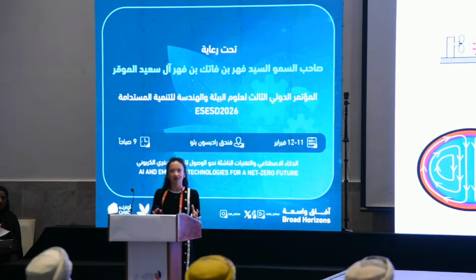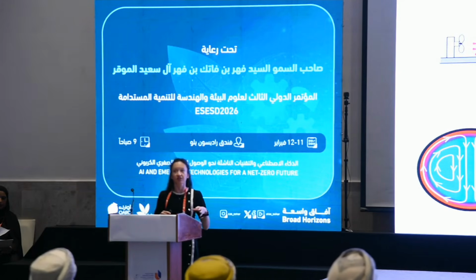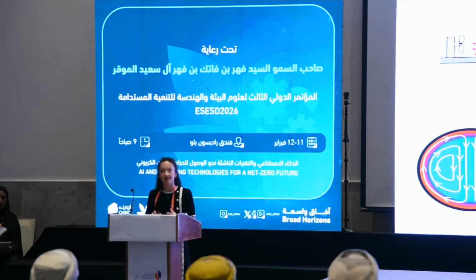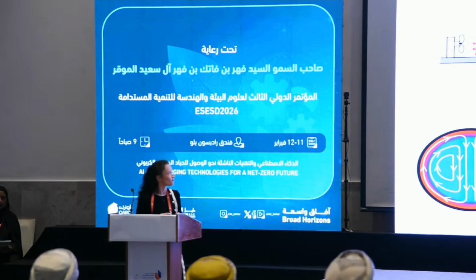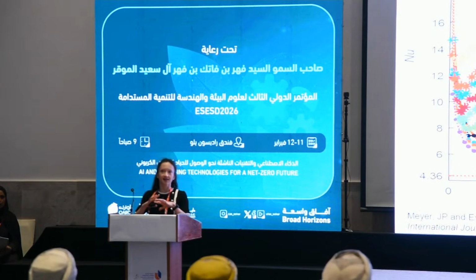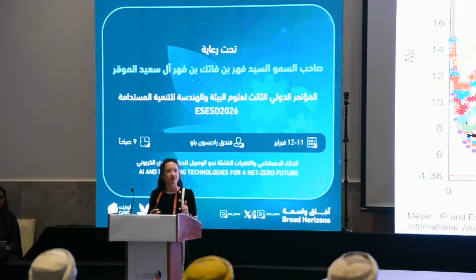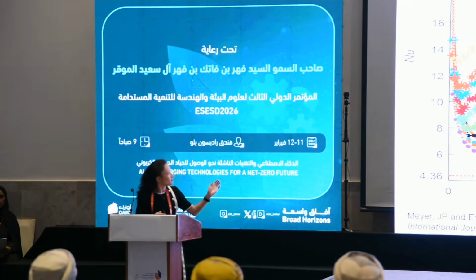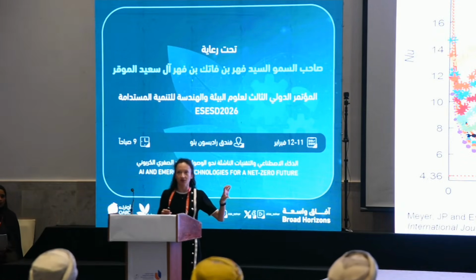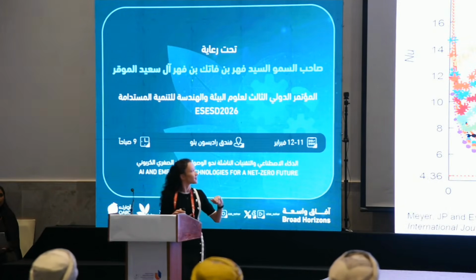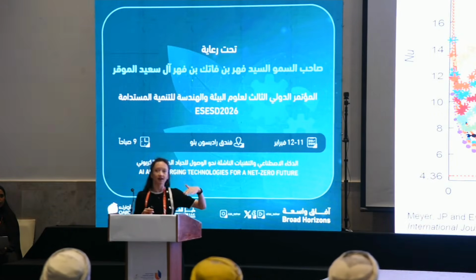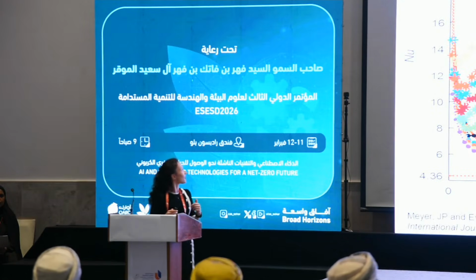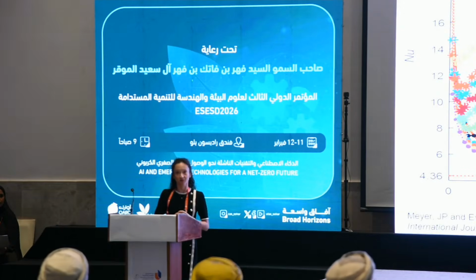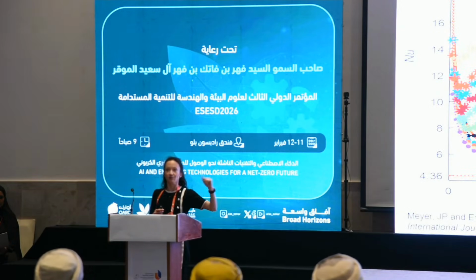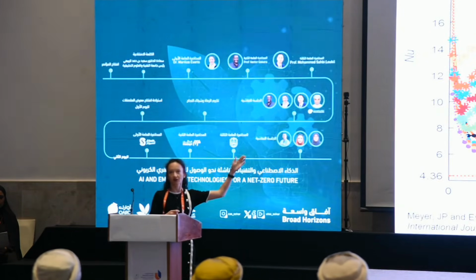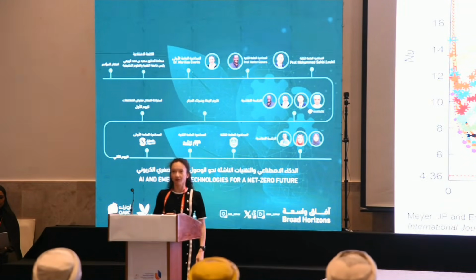So I spent a lot of research over the past decade looking at different heat fluxes and heating conditions, as well as diameters, to better understand this thermohydraulic behavior of mixed convective flow. And this graph basically summarizes a set of experiments and the effect of tube diameter and heating conditions specifically. So at the bottom, we have the smallest, in this case, results for a diameter of 4 millimeters, different heat fluxes. Then we have in the middle the stars. We have a slightly higher diameter of 11.5 millimeters, and then at the very top we have the 19 millimeter tube results. So this gives us the Nusselt number as a function of axial position, and it basically explains to us how the heat transfer coefficients will decrease from the inlet towards the outlet of the tube.